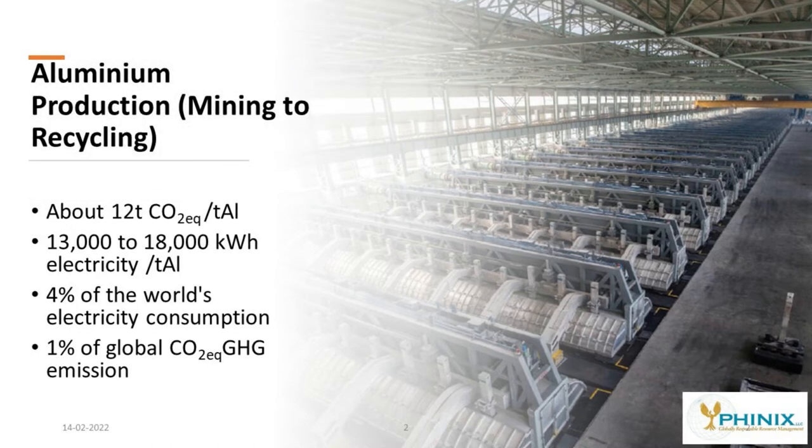Slide number two is aluminium production, mining to recycling. A couple of points: about 12 tons of carbon dioxide equivalent per ton of aluminum. Second point is about 13,000 to 18,000 kilowatt hour of electricity required to smelt or to produce 1 ton of aluminium. And it requires about 4% of the world's electricity consumption and 1% of global carbon dioxide equivalent greenhouse gases emission.